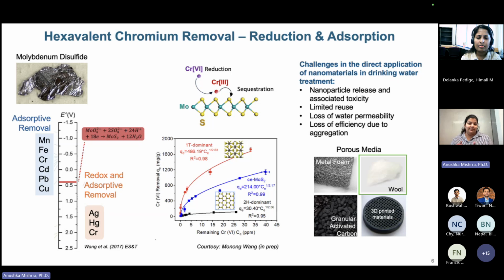However, nanomaterials pose a lot of challenges. The use of nanomaterial itself can be potentially hazardous if there is nanoparticle release, and we can also have problems with aggregation of nanomaterial - they seem to become larger particles over time and lose their efficiency. There are also issues with water permeability. If you're looking at a scale-up technology where you want to run water at high flow rate, having a nanomaterial can often block the sites where water flows through. That's one of the problems associated with using a nanomaterial itself.